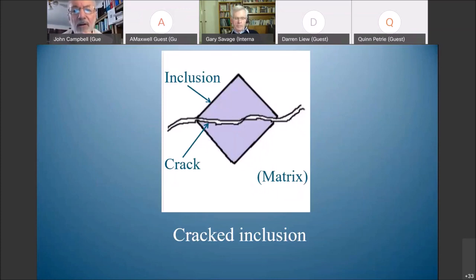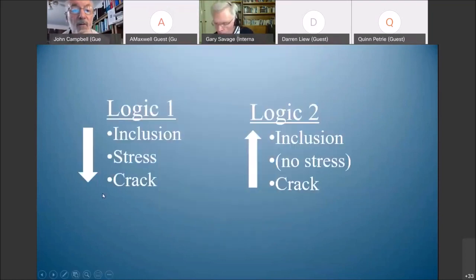The reality, and the way to describe this scenario of the cracked inclusion, is this: the crack is there first. The inclusion grows on the crack, and stress is never involved once. Now, what you can see is that the thinking of our metallurgy starts to be absolutely reversed. So here we've got the normal logic of inclusion first, applying stress, which results in a crack. And now we're going to reverse this logic, saying crack was there first.